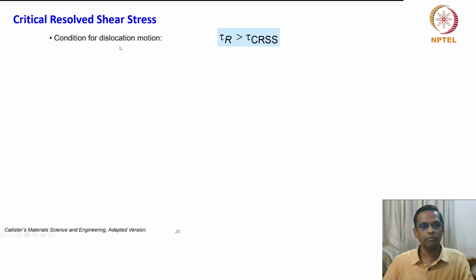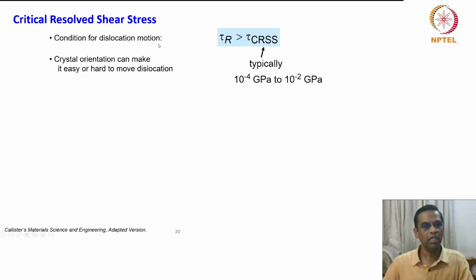That means it is a kind of condition for dislocation motion. If you recall, we have also seen the stress required to move a dislocation. So the Peierls-Nabarro equation, if you recall, is something similar to that. You can relate that. Of course, there it is assumed that the crystal is free of any other dislocation, just one dislocation in a perfect crystal. But here we are talking about a bulk. The initial condition could be of any kind, but here also it is a single crystal. The condition for dislocation motion: tau R should be greater than tau CRSS. The resolved shear stress should be greater than the critical resolved shear stress that is required to move the dislocation. That is how you should look at it.